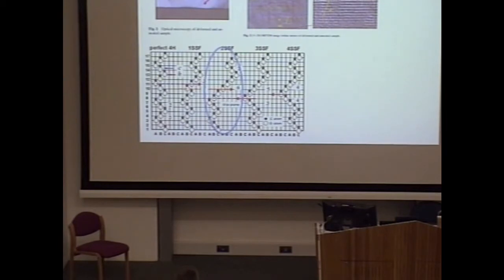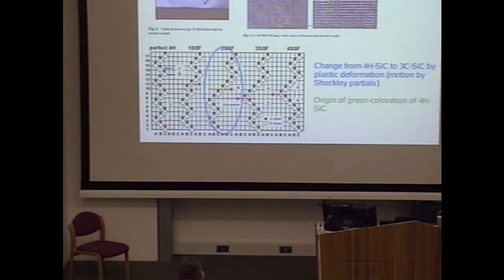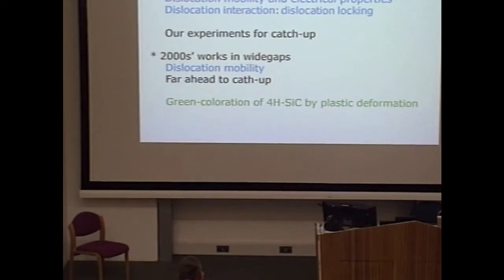So just say that this part becomes 3C structure, not 4H structure. From this information, we can understand the change from 4H silicon carbide to 3C silicon carbide by plastic deformation, by motion of Shockley partials, two partials, yeah? This is the origin of the color change of silicon carbide. So,